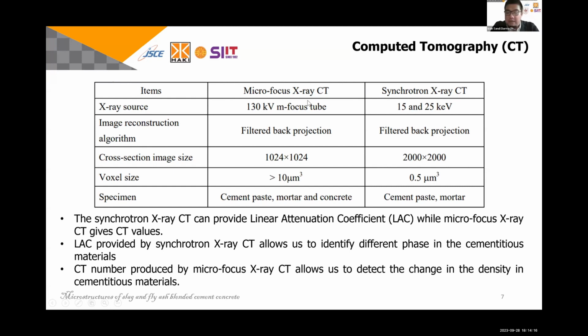But again, with X-ray CT, not only the image, we could achieve many things. Besides the image itself, we have a CT value, and for synchrotron X-ray CT, we have the LAC, linear attenuation coefficient. With both CT value and LAC, we could make a good relationship to the phases of the microstructure itself. As I explained before, LAC provided by synchrotron X-ray CT allows us to identify different phases in cementitious material. It's very easy compared to XRD.